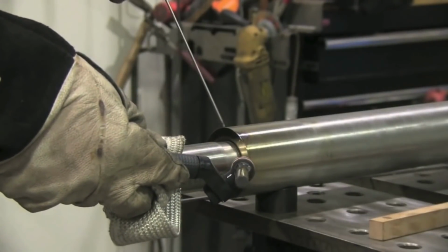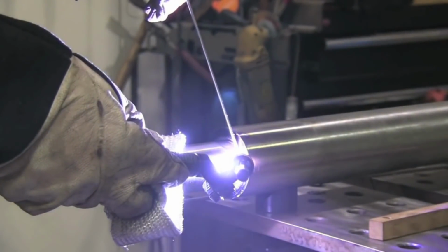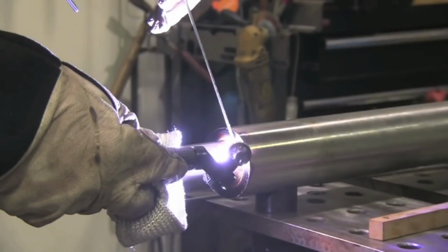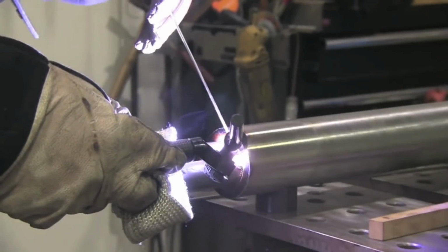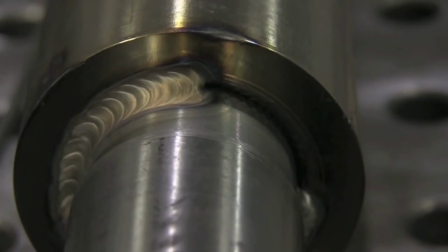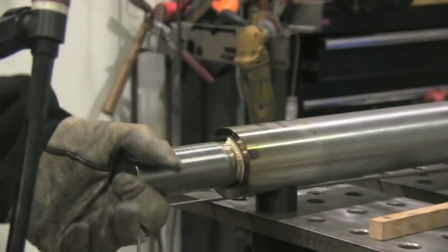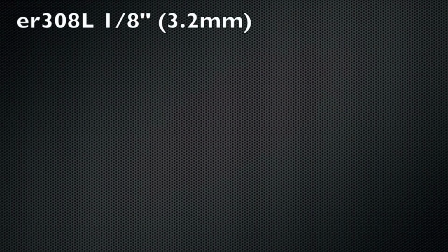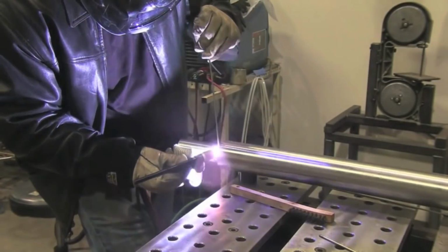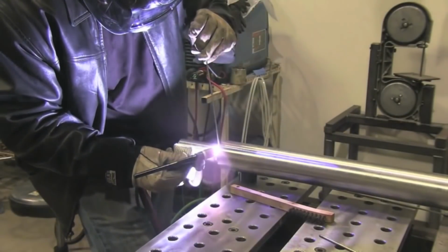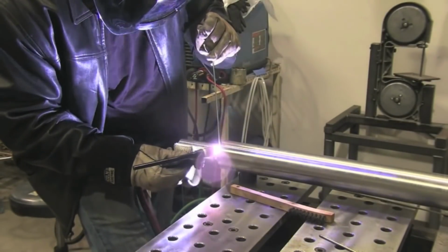Now this is a shaft that I welded a couple of years ago. It goes in some kind of food service poultry processing plant or something like that, and these ends had to be replaced, and so the first pass was done with a 3/32 rod, just dipping it in and out of there so that I could get good penetration up into that little groove there. And then after the first pass was done, came across it with a larger wire and weaved it. And the reason for the large weld there was because there had to be a radius turned on that shaft. A nice smooth radius was required. You know, in any kind of food processing plants, they don't want anything that'll trap bacteria, so everything's got to be smooth and without any crevices and rough places.